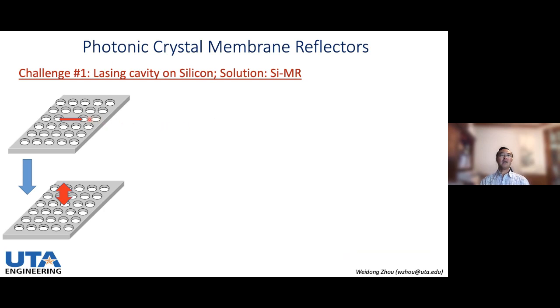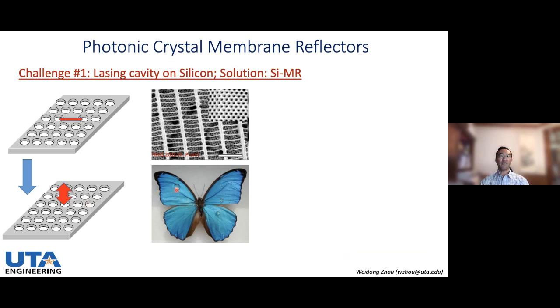So the idea here is, instead of looking into a defect mode laser where you have a periodic structure with a removed hole to have a defect cavity, which is what we used as a band gap material, we looked into whether we can have a reflector made in a perfect two-dimensional periodic structure where you have 100% reflection, to form a mirror based on this single layer structure. And indeed it works. In fact, later on you can see people talk about this now, it is in fact like butterfly wings with shiny color.